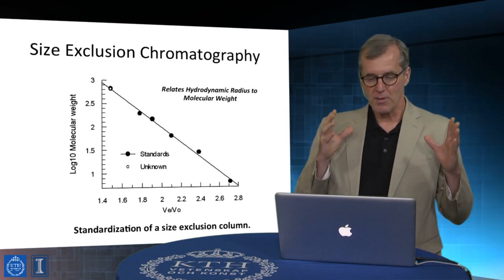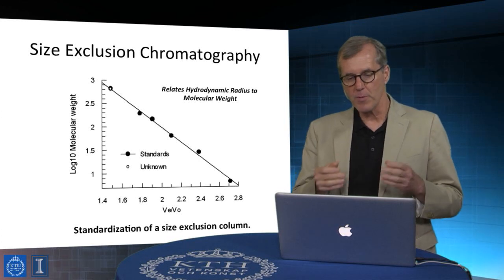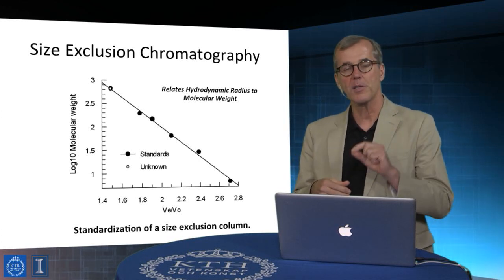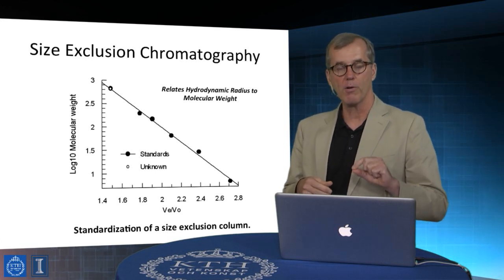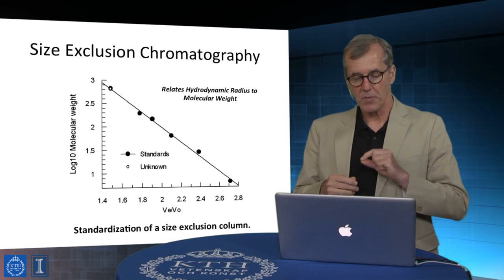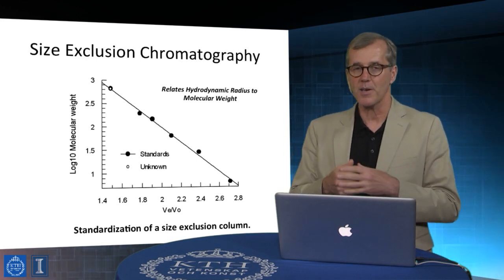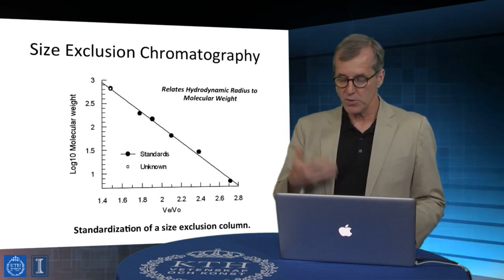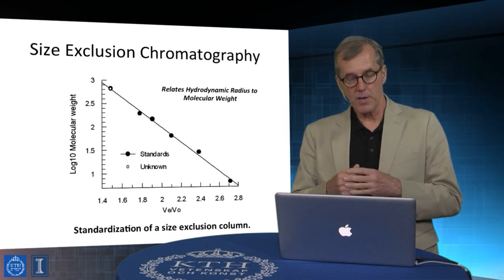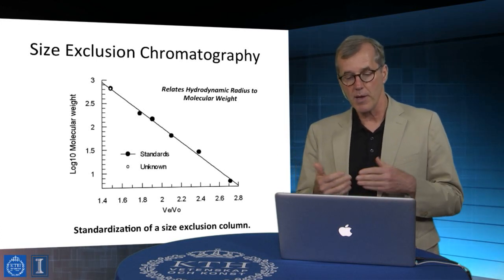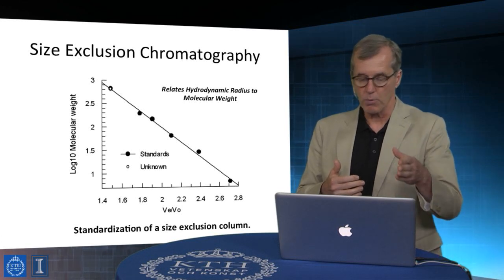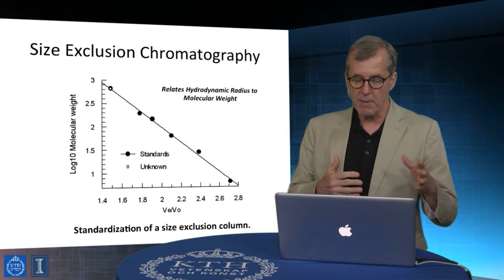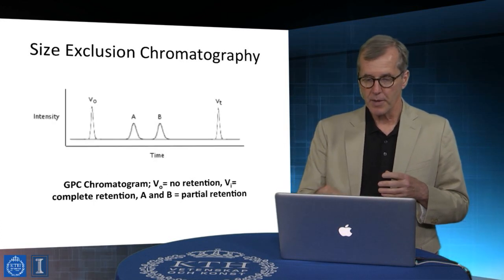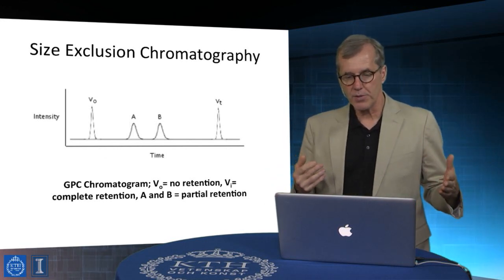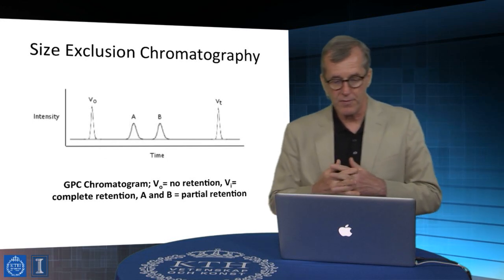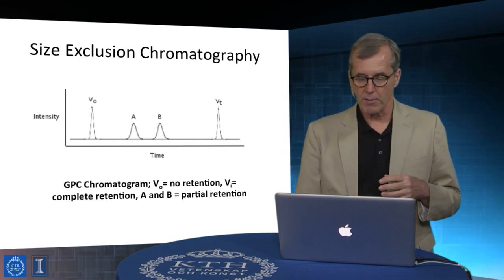So the references here are everything, and when you perform the references, you can then in fact say where it is that your unknown fits on the known elution profiles of these known standards. And then the standards can be characterized, via complementary methods, usually by a lot of work. But then the unknowns are characterized in a much more simple way by comparison with the standards, using relationships such as shown schematically in the slide. Okay. And the parameters that are needed to do that are just basically taken off of the elution chromatogram.